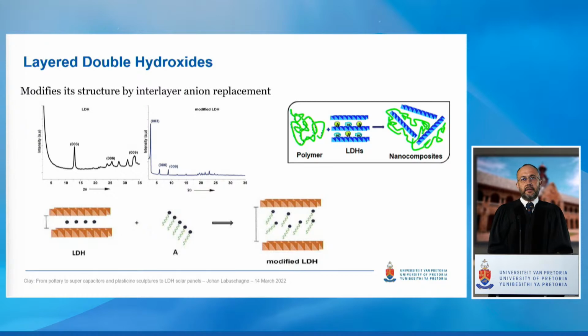The next thing we can talk about, after we've now discussed the brucite-like layer and its structure and different metals in it, is the interlayer. We can remove the carbonate, which is the most common interlayer ion, from the structure and put other things in there. At the bottom, we can see that we've taken the LDH, removed the black dots, the carbonate, and replaced it with some sort of surfactant, in this case, an anionic surfactant. This now intercalates into the LDH as it sits inside the layers. On the top right, we can see the same principle, but this time the LDH is intercalated with polymer chains as they sit in the interstitial position.